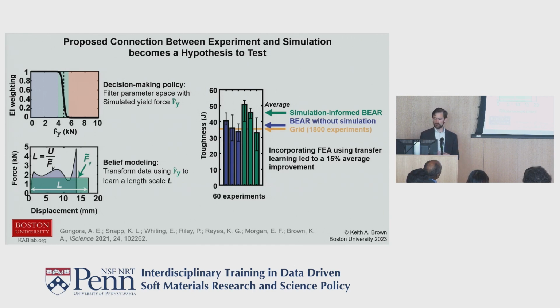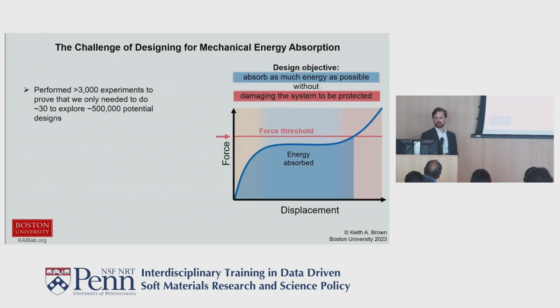And so this was a very important lesson, because it showed us that we can use this approach to find structures very efficiently. We have ways of bringing data in. And so this kind of took us to the end of this cross-barrel story. And at that point, we sat back and thought, okay, we had this parameter space. It was 500,000 possible structures. We studied 3,000 or so of them. And what we learned at the end of the day is we only really needed to have studied 30, and we would have gotten as much out of this space as we needed to.